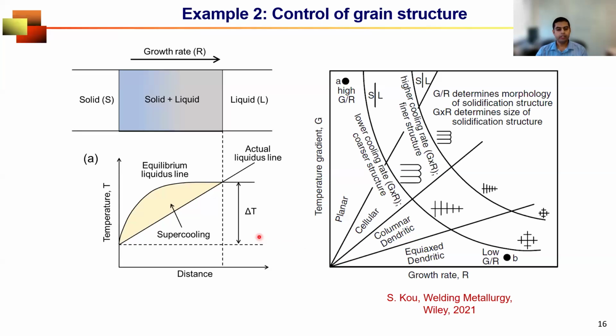You can very easily find out. You just need to calculate the temperature distribution that I showed you how to calculate. Once you do that, you get the temperature gradient and growth rate and readily find out your solidification morphology. Second advantage: along this hyperbolic line, G times R, which is temperature gradient times growth rate, is constant. That value gives you the size of the grain. This product is called the cooling rate, and that is directly connected to the size of the morphology. Now, let me give you examples of both of these.